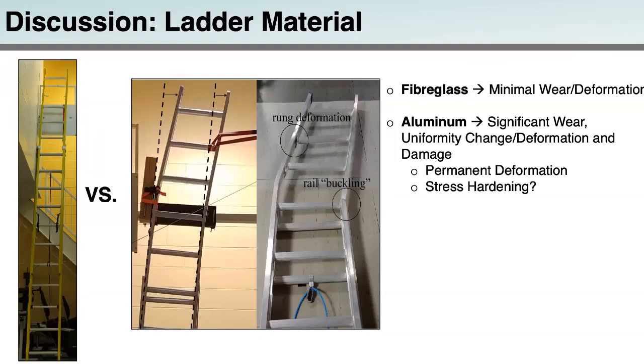In contrast to the fiberglass ladder, the aluminum ladder rails underwent permanent plastic deformation and failed to return to the original position following each test, even after we had removed the 250-pound weight from the ladder. This resulted in cumulative and increasing deformation across the tests in the aluminum ladder side rails, which in turn led to faster cumulative fatigue failure in the aluminum ladder in contrast to the fiberglass.